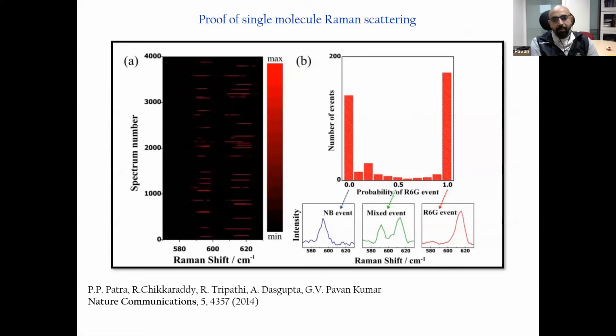Now, this swarm of nanoparticles has some very interesting statistics. For example, if you look at the Raman scattering signature arising out of this kind of swarm, you ask, how does the molecular signature fluctuate as a function of time? What is shown here is a small part of the large experiment. In this particular case, what is plotted is the spectral number as a function of Raman shift. Now you see the fluctuation as a function of time, and you go back to the analysis which I spoke about, the bianalyte technique approach, where you can extract the statistics out of this particular interaction. Again, what you see is the proof for single molecule Raman scattering in such assemblies.